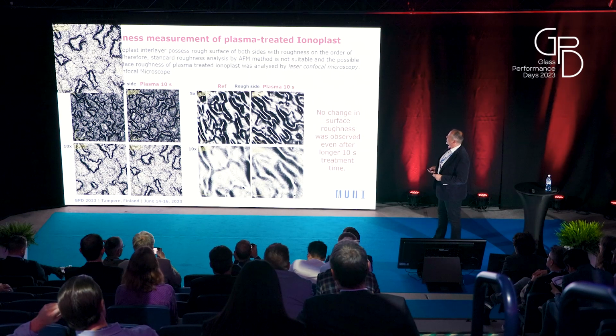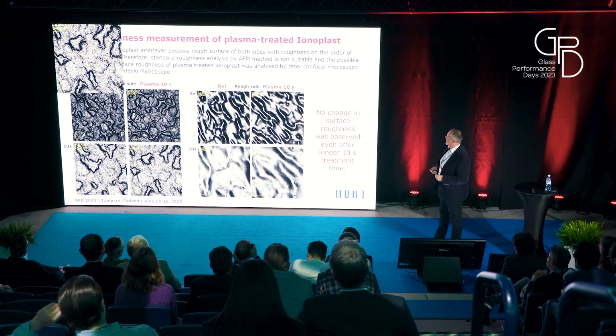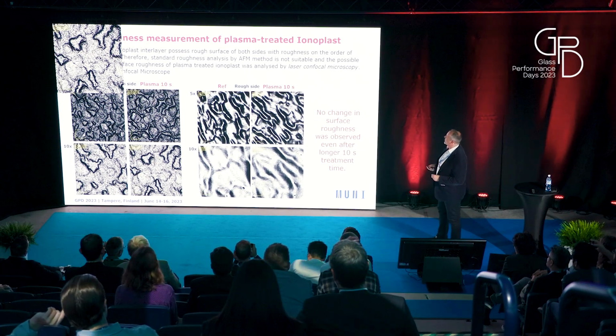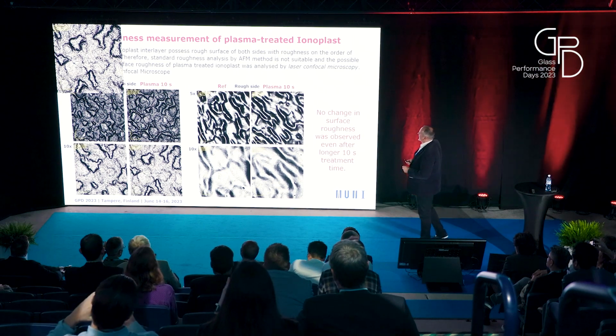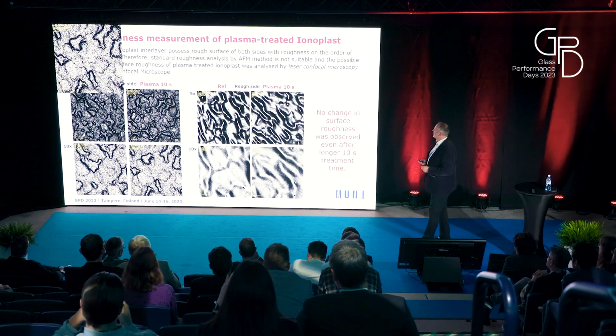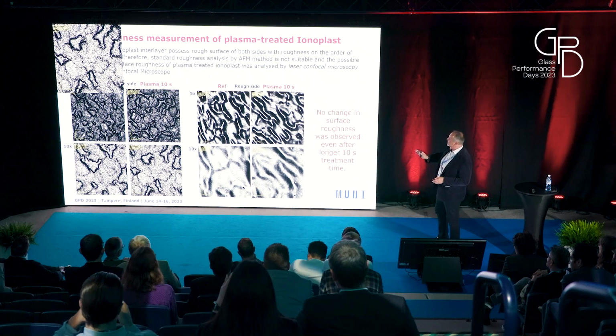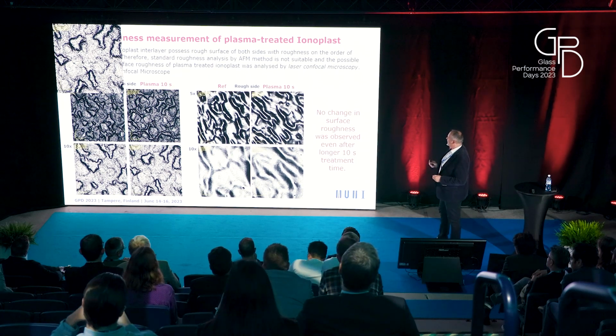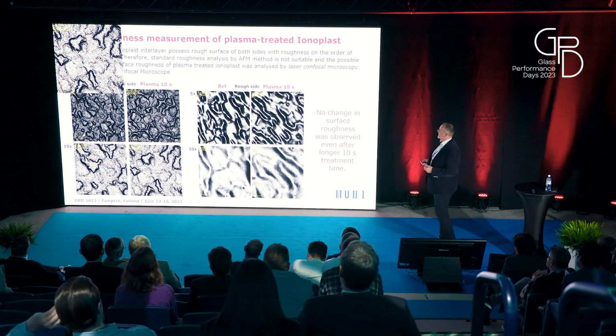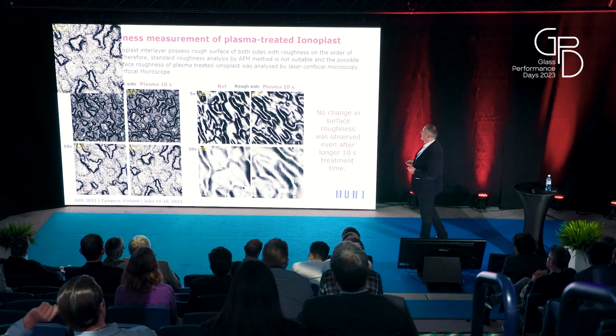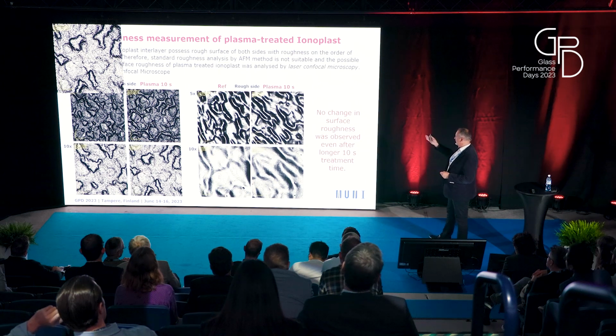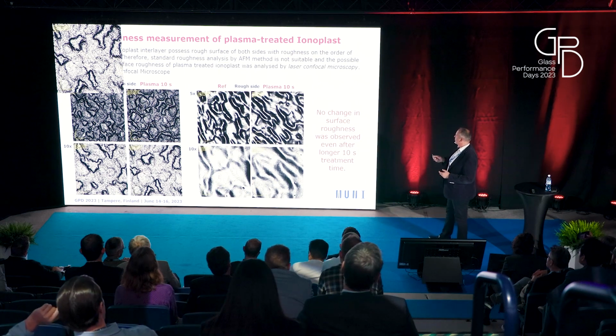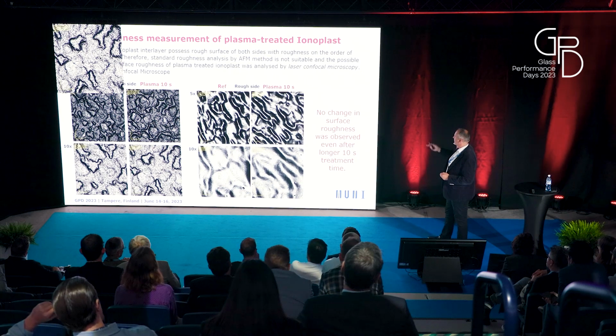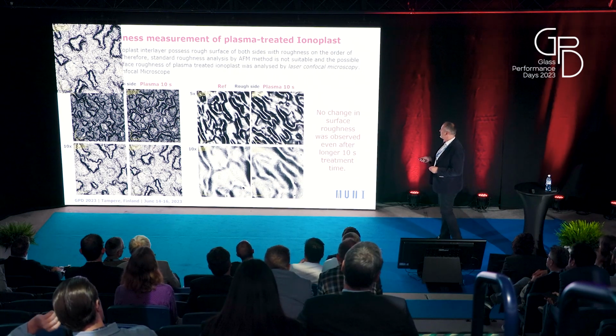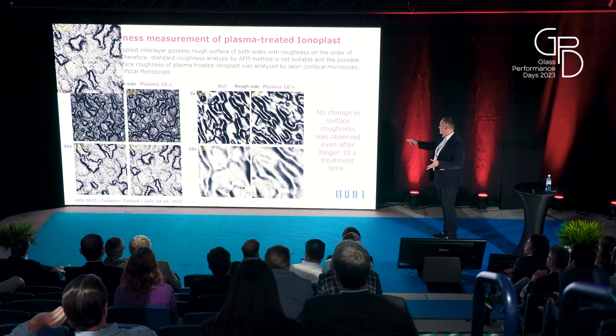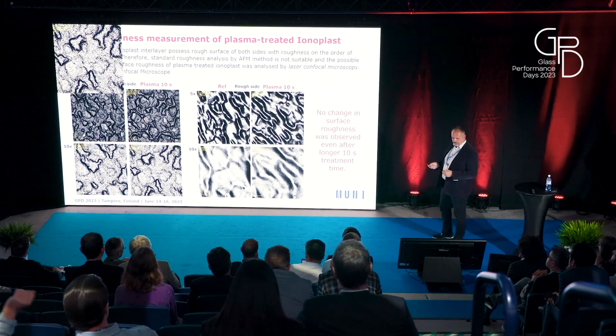We investigated also the roughness, using a confocal microscope, and there are double pictures at magnification 5 and 10 times, on both sides, smooth and rough. And we could not use atomic force microscopy because of the roughness of this SentryGlas. The results which we obtained showed us that there was no change in surface roughness. We didn't observe it even after longer treatment with a duration of 10 seconds.